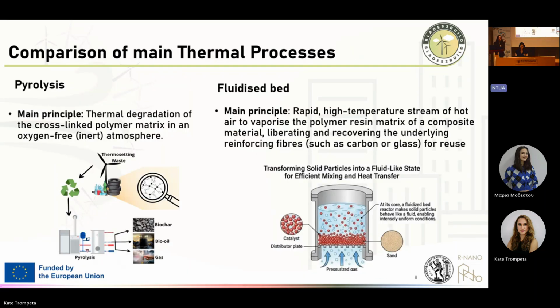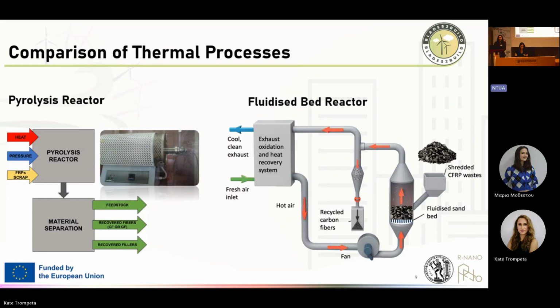So to focus on the two main thermal processes, there are pyrolysis and fluidized bed. The main principle of pyrolysis is the thermal degradation of the cross-linked polymer matrix in an oxygen-free, inert atmosphere. And in fluidized bed, we have a rapid high-temperature stream of hot air to vaporize the polymer resin matrix of the composite material, liberating and recovering the underlying reinforcing fibers, for example carbon fiber or glass fiber, for their reuse. Here you may see some indicative reactors. For the pyrolysis, actually we are using heat, pressure, and the scrap, which is the feedstock.